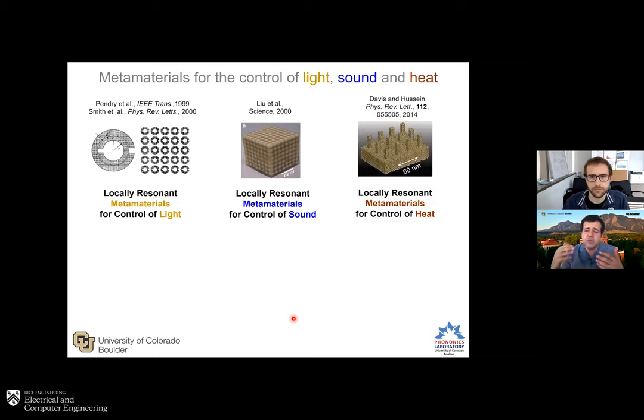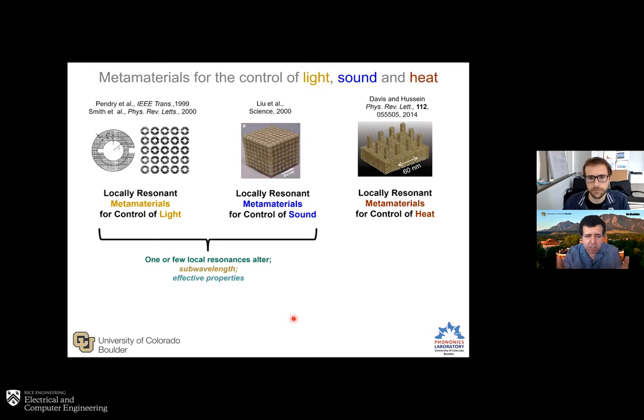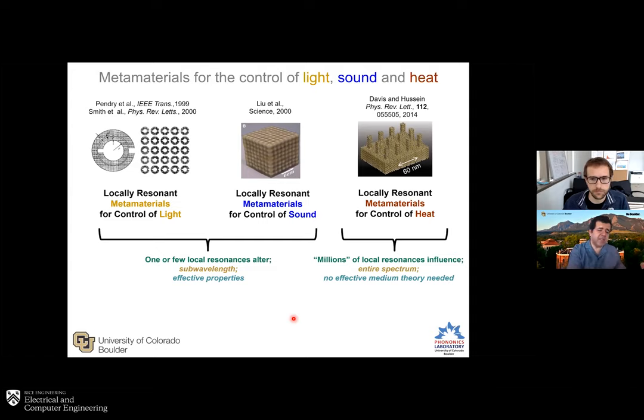So this would be a metamaterial for the control of heat. And as I've explained throughout the talk, if you're familiar with the more classical metamaterials, you can immediately see a wide range of differences. For example, where the classical ones utilize one or few resonances, here we're utilizing millions of resonances. Whereas in a classical metamaterial, you're mostly interested in the sub-wavelength regime, here we're interested in the entire spectrum.